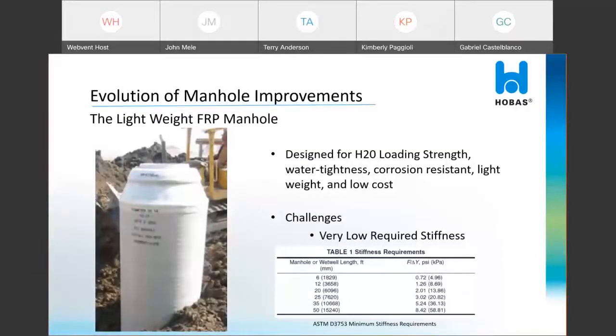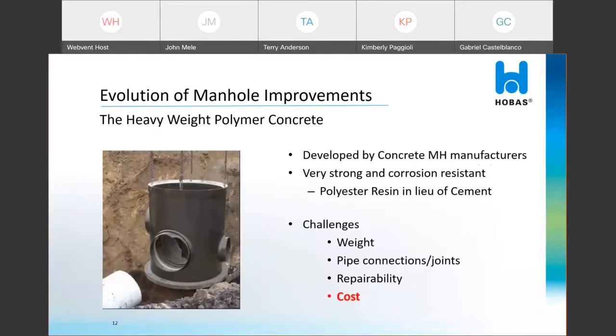Rightfully so, manholes then evolved to use lightweight FRP manholes. This was a great solution because it offered incredible longevity, corrosion resistance, lightweight, and all at a low cost. However, the thicknesses used were extremely low, resulting in a pipe that was harder to handle and was more prone to buckling. A good alternative to lightweight FRP manholes has been heavyweight polymer concrete manholes. These manholes are stronger than the lightweight FRP while still being corrosion resistant, since they are made using resin in lieu of cement. This type of manhole, however, is very heavy and has a very high cost.